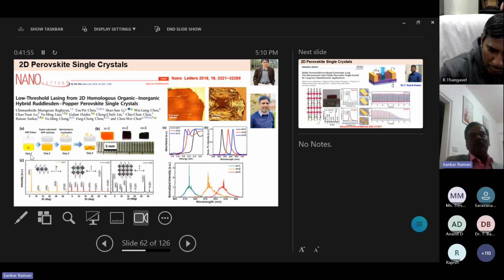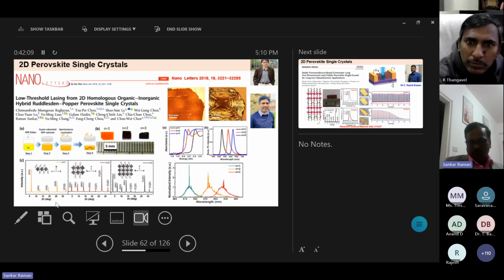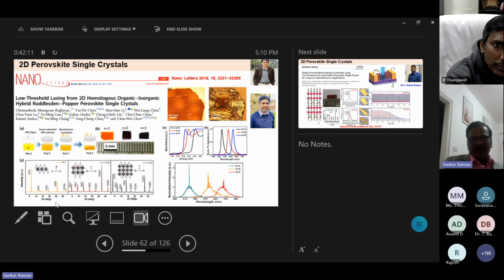Another thing: how can you claim this is an N equal to 1, N equal to 2 or N equal to 3 layer? You can see clearly from the XRD. In the 2 theta, below 10 degrees, if only one peak appears, it belongs to N equal to 1. Then in the second one, below 10 you can see two peaks, which means N equal to 2. In the third one, you can see almost three peaks.